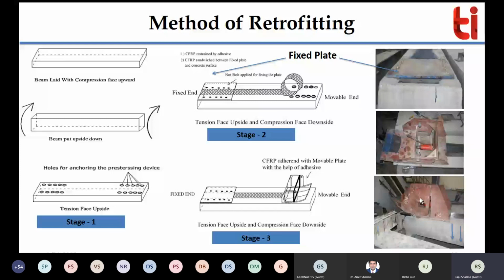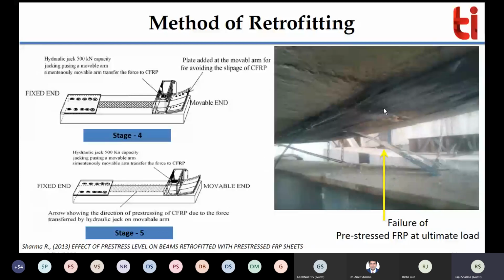And then we applied the loading. On the right side you can see we are applying the loading. There was a failure in the FRP, in the form of strips basically. And you can see that the concrete surface, the near surface or cover, is stuck with the CFRP after failure, but the load deformation behavior is significantly improved after applying the CFRP.